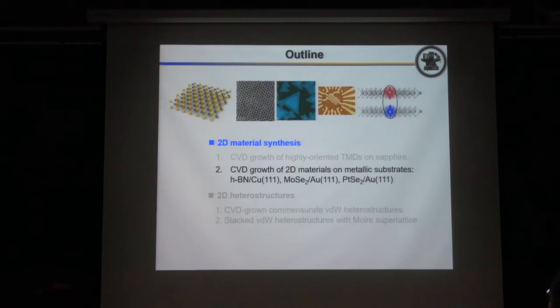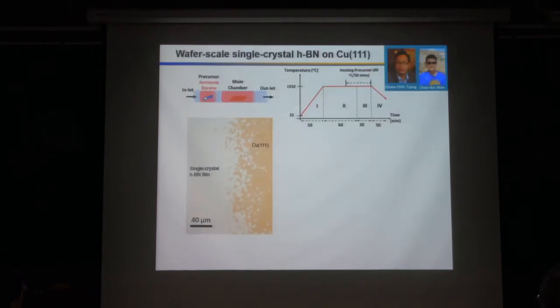So the second one is we are trying to grow material on metallic surfaces. The first example is we grow hexagonal boron nitride. Maybe you know hexagonal boron nitride is a layered insulating material, and very important as an interfacial layer. If you want to fabricate a 2D semiconductor FET device, and you use boron nitride at the interface between the semiconductor and the dielectric layer, it can block the influence of the charge at the oxide layer. So this is a very important material.